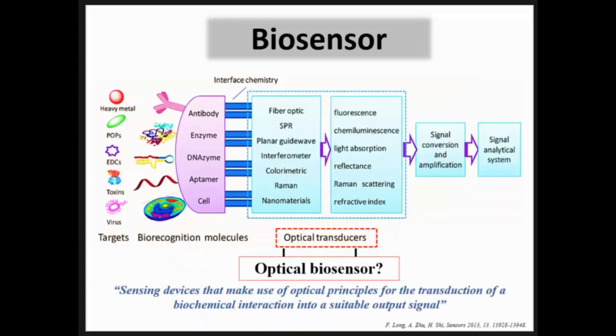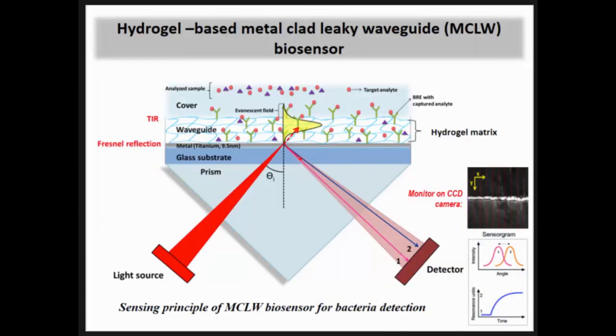Particularly today, I would like to talk about the optical transducers, whereby I use a few of these optical properties in order to generate the signal for my sensor. To be more specific, my sensor is a hydrogel-based metal clad leaky waveguide biosensor. It's actually a 4-layer device consisting of a high refractive index material as a glass substrate. We have a metal layer here, about 9.5 nanometers, just enough to have a Fresnel reflection. We have a waveguide layer made from the hydrogel matrix, as well as a cover layer for the system to flow the water later.